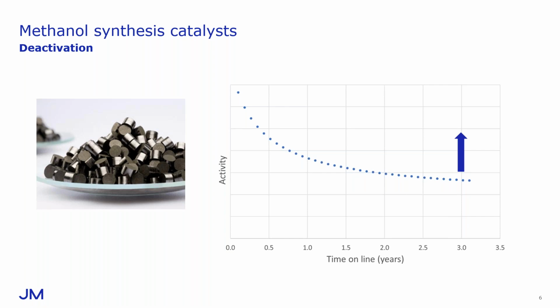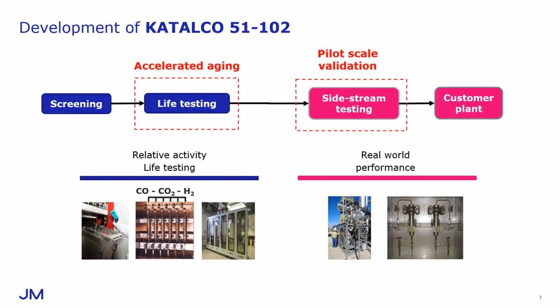So with 51-102, we decided to take a different approach. And so instead of looking to try and improve the initial activity, we targeted improving the long-term stability of the catalyst. Now, this change in focus created an immediate challenge for the research project, in that whilst it is relatively easy to measure the initial activity of a catalyst, it is much more difficult to evaluate over a reasonable time frame what the aged activity is likely to be under any given set of operating conditions.